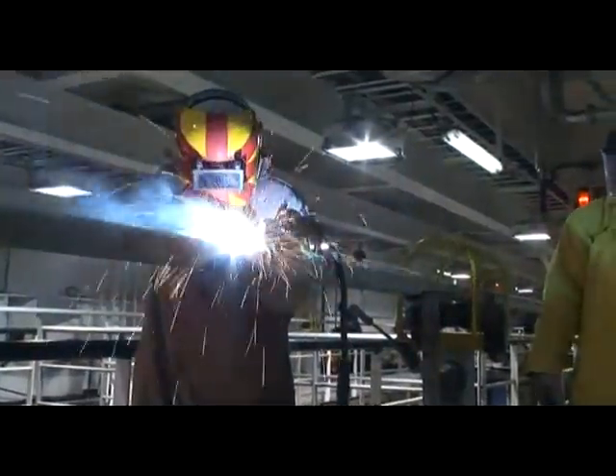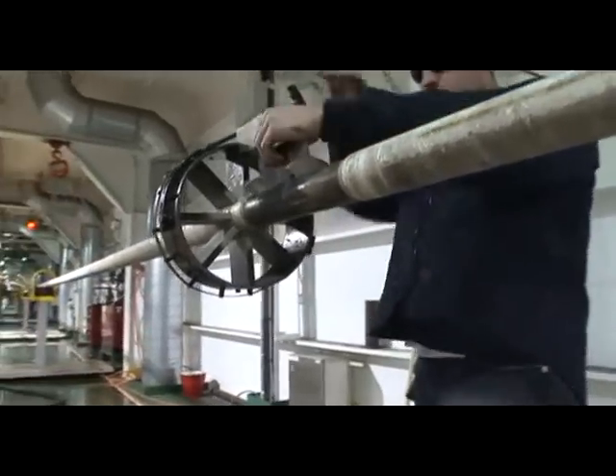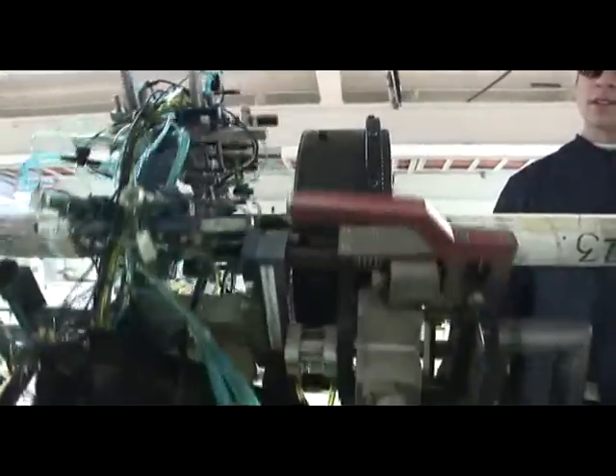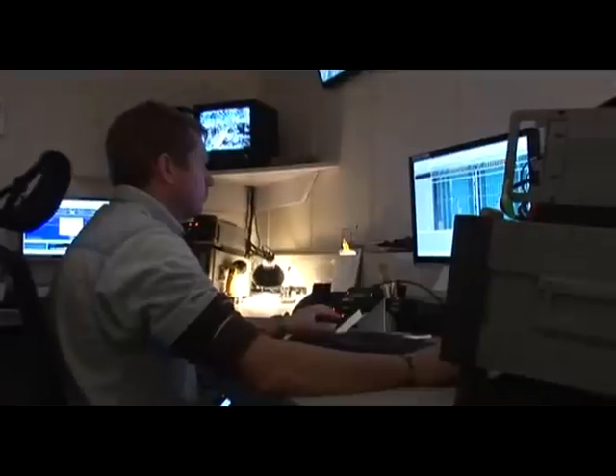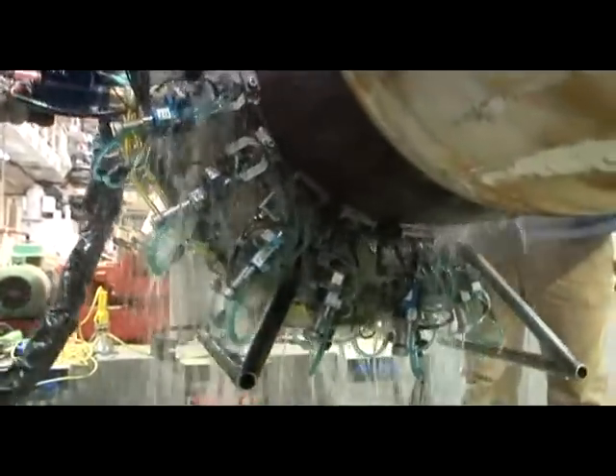The fillers and end cap welds are laid using stick rod welding. After grinding, the pipes reach the non-destructive testing station. Upon completion, all welds, or field joints as they are called, are quality tested and approved. The automatic ultrasonic testing unit, a non-destructive testing method that uses sound waves and clean water, determines the quality of the weld.